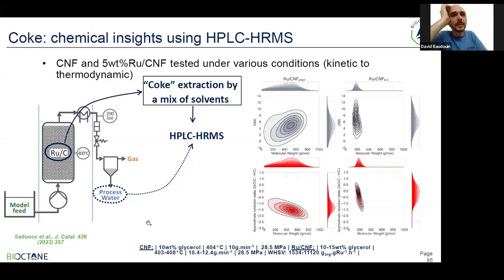Next slide, please. On the right, so I'll come back to the former, this one. On the top left, that I presented already, is what was observed after the catalyst was exposed to intermediate reactions. So all the organics were not converted, but most of them were converted. And the one on the right are the extracts obtained after a test done in the kinetic regime, so only 20% of the organics were converted. And you see that there is a huge difference, first in the molecular weight of the deposits, but also in the double bond equivalent. It's a bit higher, but overall it's not so far from it. They are generally more, particularly considering that the molecular weight is lower.